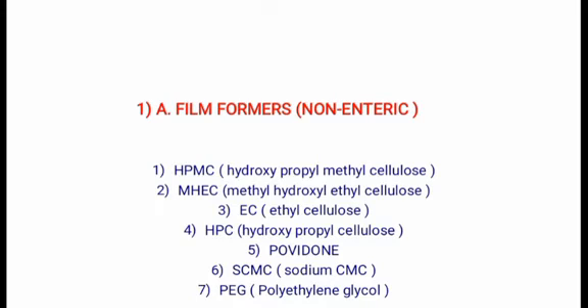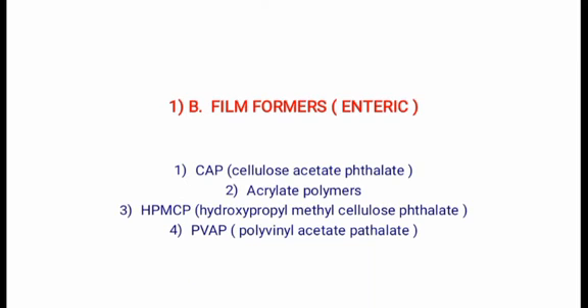The seventh one is PEG, that is Polyethylene Glycol. It is divided into two parts: lower molecular weight PEG and high molecular weight PEG. Lower molecular weight PEG ranging from 200 to 600 are liquid at room temperature and are used as plasticizers. High molecular weight PEG ranging from 900 to 8000 are white, waxy, and solid at room temperature.